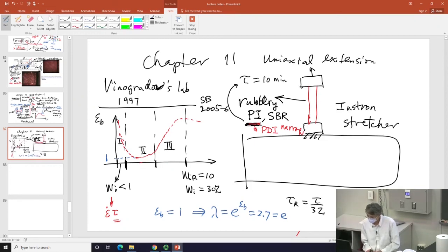Okay, so I'm just trying to first give you what is already known. There are 4 regions. And the bad news first is that it breaks in all of the cases except region 1. If you patiently do it, the only time it will break is through some capillary instability, surface tension kind of related, and that's not what we're interested in.